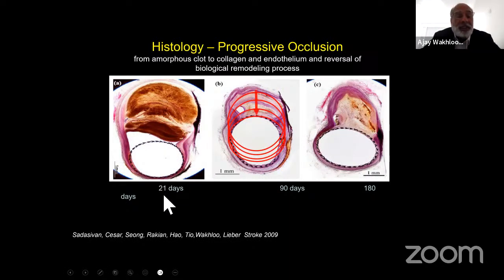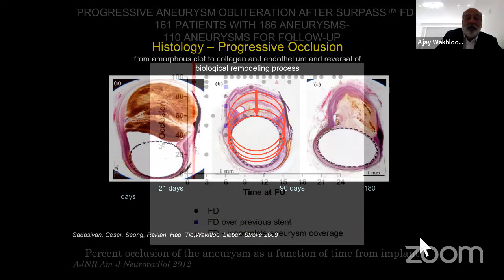Interestingly, on histology here at 21 days, you have clots. And then over time, the collagen deposit occurs from the perimeter of the aneurysm towards the neck. So even if an aneurysm that's treated with a flow diverter is not completely occluded, what you will see is that it will be stable and the likelihood of rupture is low. It's not zero because we are dealing with biology, so there are some changes happening in the wall infrequently that may lead to rupture, and we still don't understand that. And a complete healing is then done here in the rabbit model about 6 months after deployment of the device.